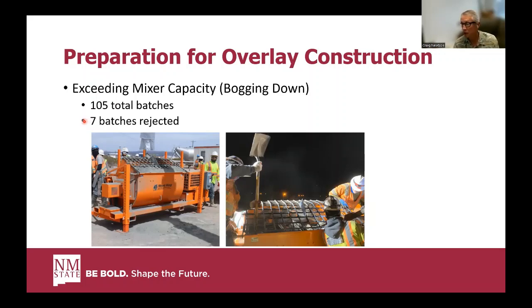facilitate a performance specification. So since the mix was prescribed, those 7 batches that were rejected, the money for those batches came out of NMDOT's pockets, and it was NMSU doing the testing on site that rejected those batches. So when we rejected those batches, we were acting as agents of NMDOT, and NMDOT had the liability for paying for that concrete. So it's just the nature of a pilot project, an implementation project. It's not what you would want to see long term, but it certainly served the purpose that we needed it to serve at the time.